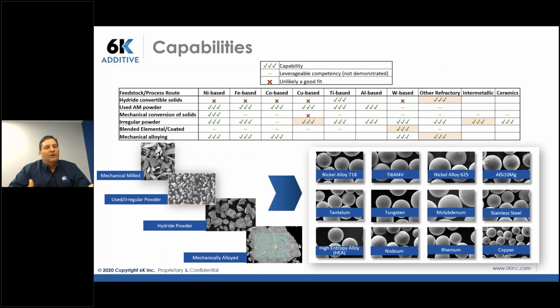So I mentioned earlier that we do the core alloys, the nickel family of alloys, stainless steels, titanium based. But we've also expanded out into starting to commercialize some of those refractory alloys. And while I won't go into the whole capability matrix, you'll be able to look at that through the recording. We have a wide variety of options of raw material inputs that we can get to those spherical powders. And so some of our core focus is mechanically milled. So where we're taking particulate materials and making them the right volume via mechanical milling. We can take irregular powders, whether it's from some other atomization technique or chemically reduced powders or even used powders.